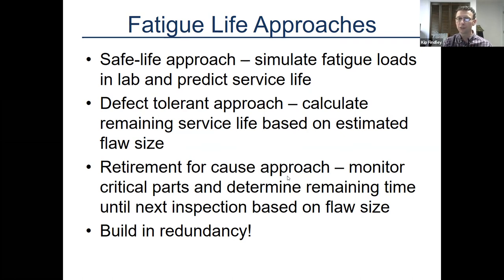But typically in aerospace, what they use is something called the retirement for cause approach for the really critical and high-end parts. They really carefully monitor the parts and the service conditions, and based on those, they can estimate stresses. Based on those, they can determine the remaining time until they need to inspect the part. So aircraft engines are inspected at certain intervals, based on how long they think the part can go before they need to look at it again to see if there's a flaw.